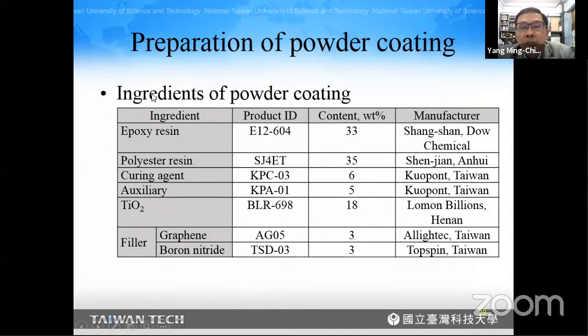And the next is the preparation of a powder coating. The ingredients of a powder coating are epoxy resin, polyester resin, and curing agent for commercial products, and also some auxiliary agent, titanium oxide, and the filler. We provided only 3% of filler, either graphene or boron nitride, for comparison.